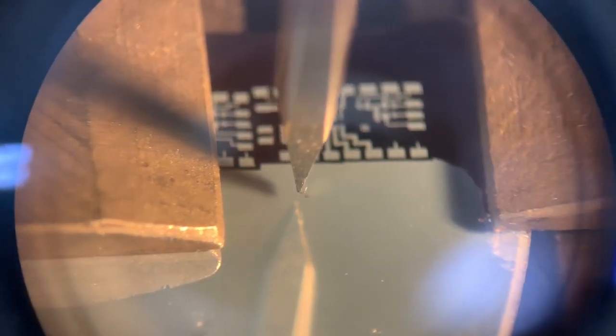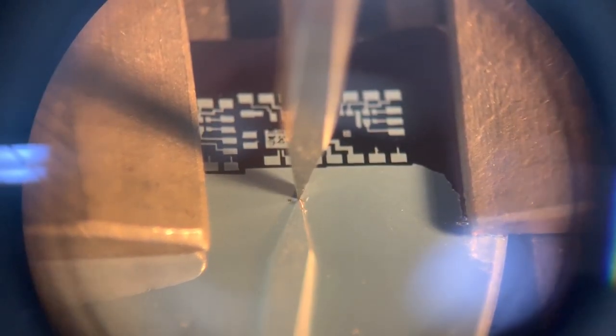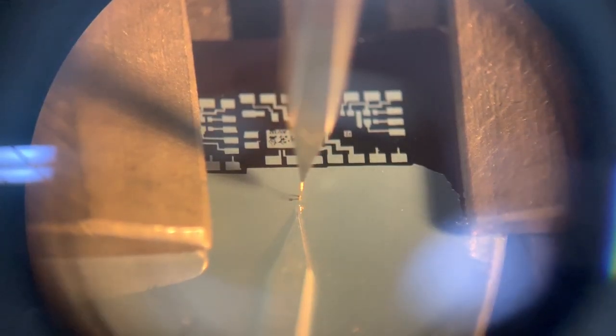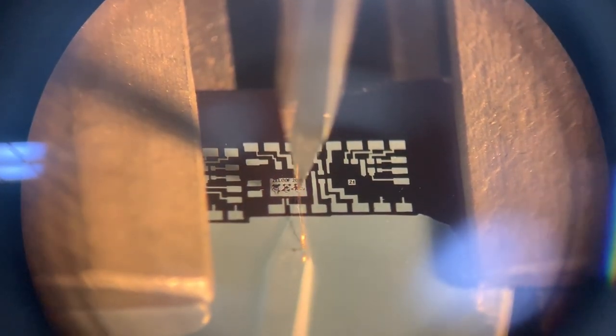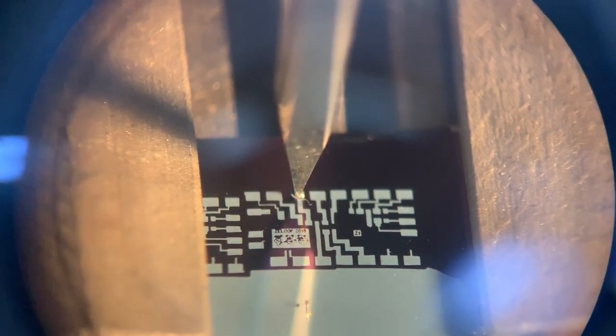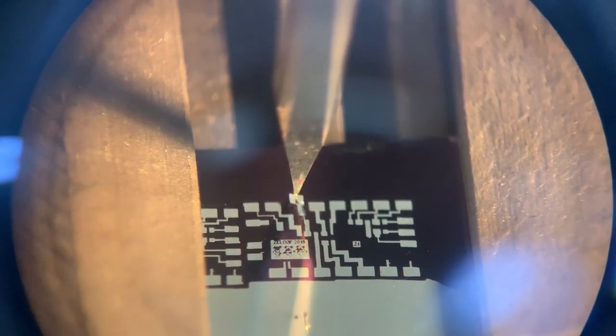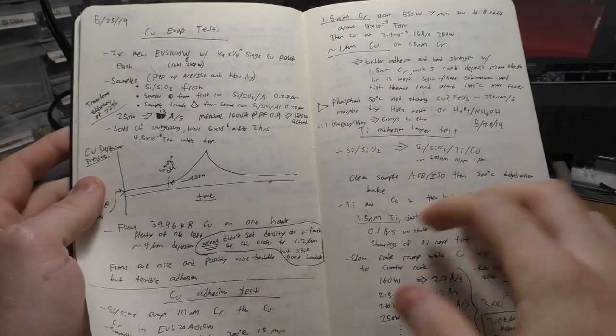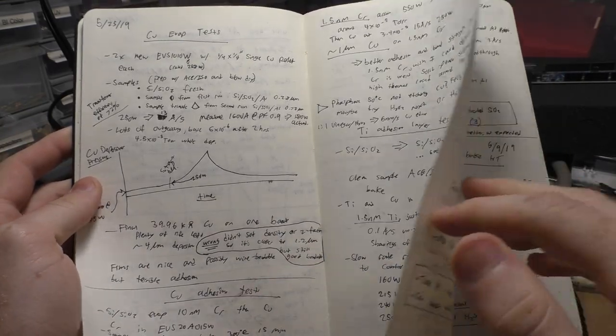But it's not always that nice. With the same exact settings, this time you'll see complete failure on the second bond. So the first one's good, but on the second one here it tears up the pad due to poor metal adhesion. This is something I struggled with for a very long time.